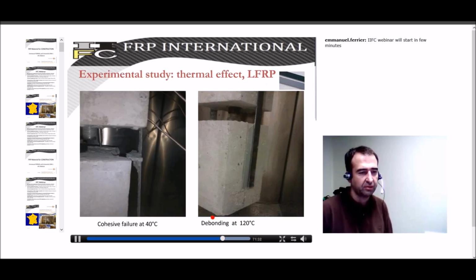About the failure mode, here you have the one tested at -30. You can see that the system, all the concrete block, is frozen. The test was done with the temperature and the loading at the same time, so it was in a thermal chamber. And then when the temperature increased, we get a very non-cohesive failure with full debonding on the FRP system.